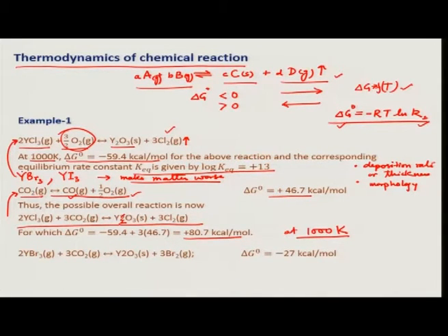What we can do is replace this yttrium chloride with yttrium bromide gas and use the same reaction, such that delta G is again negative. Once delta G is negative again, and is smaller than this number, then we can use this to design our reaction for thin film deposition. So, this is an example of how you tune the reaction chemistry and thermodynamics to suit your purpose. This delta G should be small and negative. So, that is my example 1.